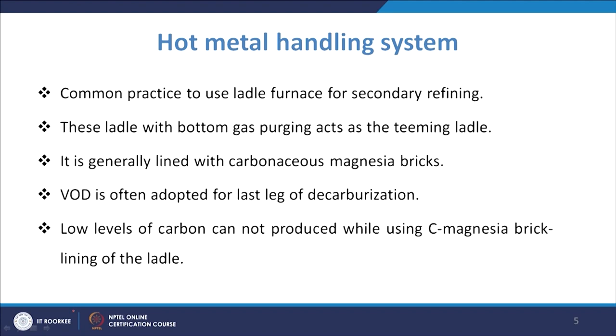Common practice is to use the ladle furnace for secondary refining. What we have earlier seen is that nowadays it is a very common practice to use the ladle furnace. So, that is a very important tool for the secondary refining process. And in that basically you have this ladle with bottom gas purging. So, the gas purging is done from the bottom, and that acts as the teeming ladle.